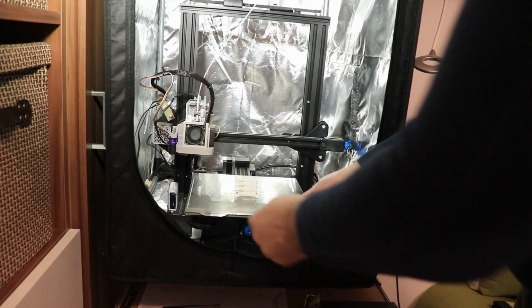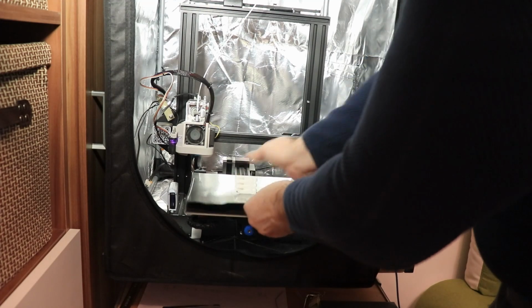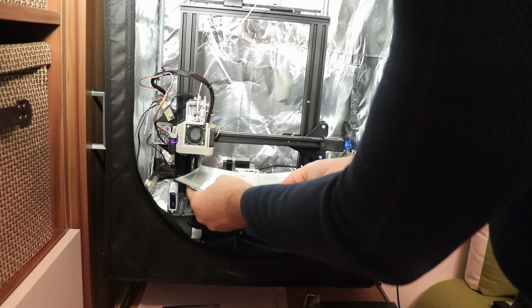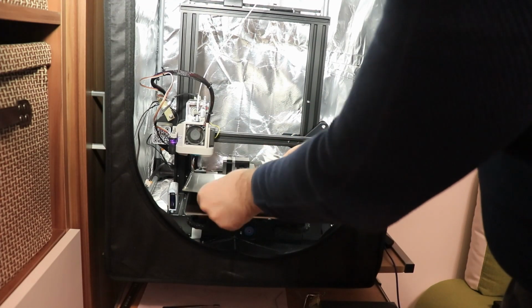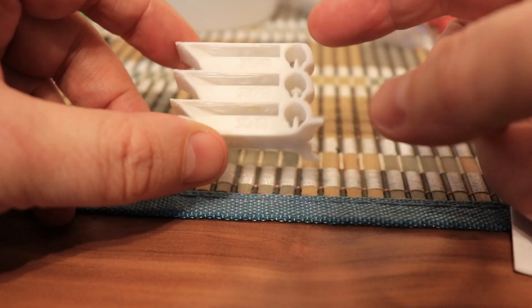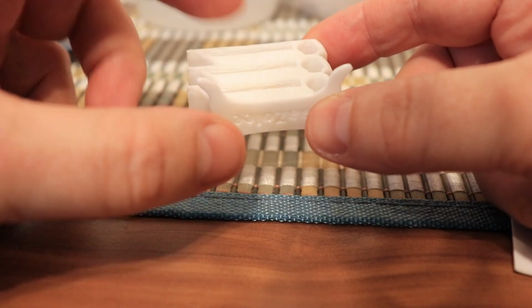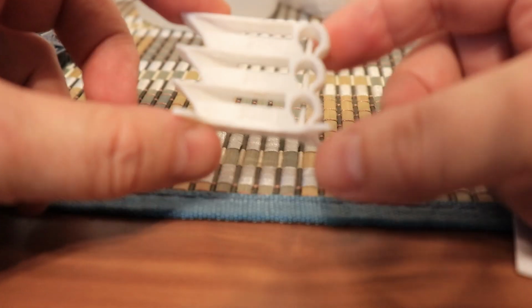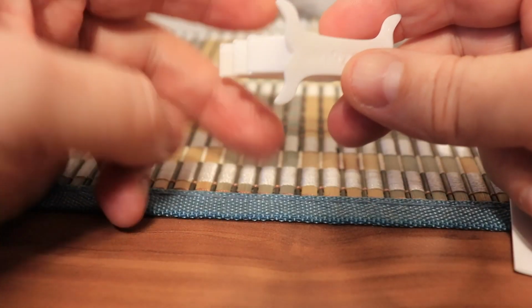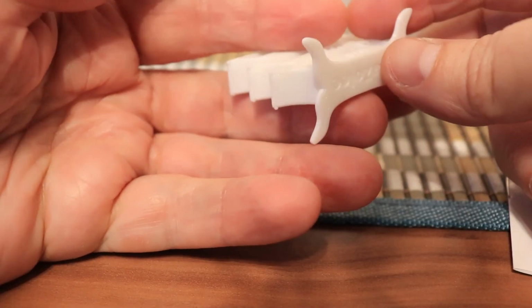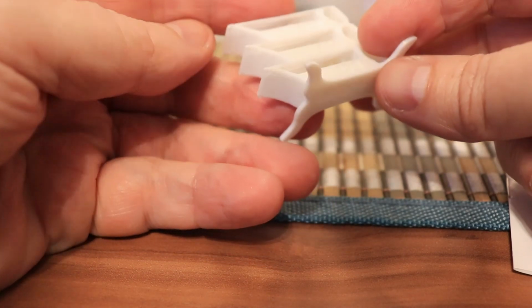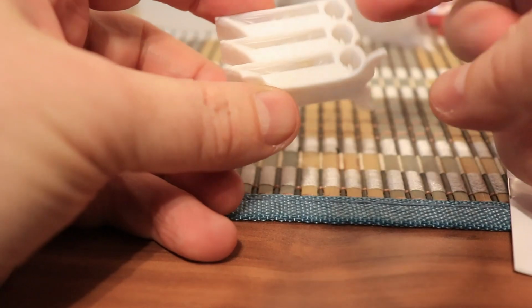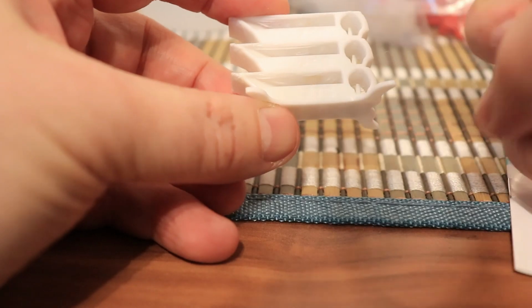The bed already cooled down. This temperature tower looks great. Maybe the bridging is not so perfect, but there is no stringing, and look at this almost perfect overhang. And now I print the test specimens on 260 degrees Celsius.